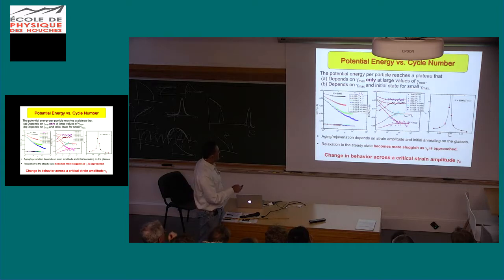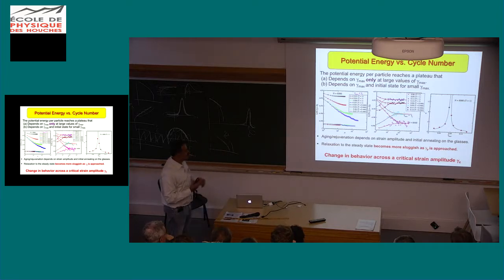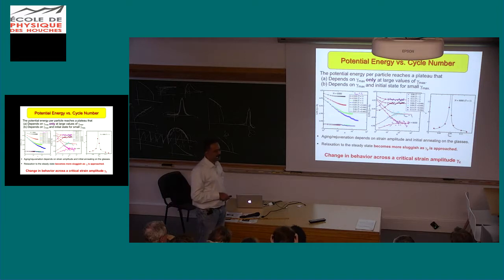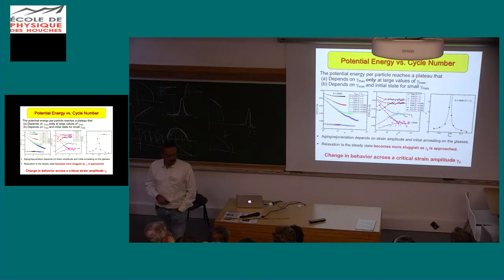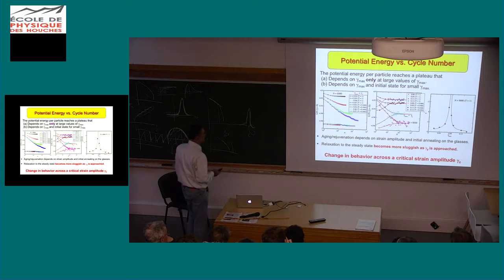The important thing to note is that when we go to larger amplitudes, these energies converge to a common value regardless of what initial configuration I start with, and so the system is somehow reaching, in quotes, an ergodic state. So the final state is independent of what I started with. And the amount of time that I take to reach this final state seems to show an apparent divergence across some threshold transition amplitude, and this is between 7 and 8%. So there is something changing drastically at that strain amplitude.